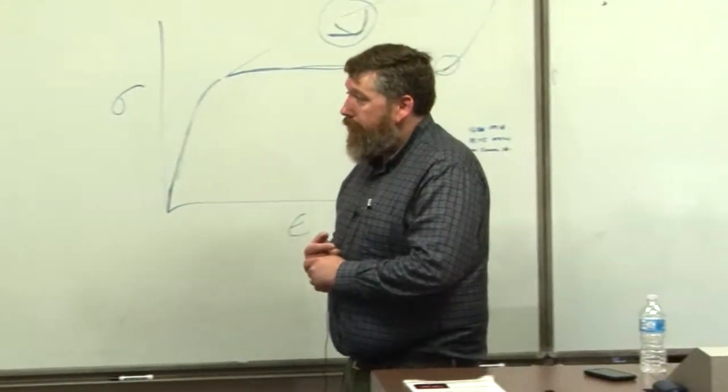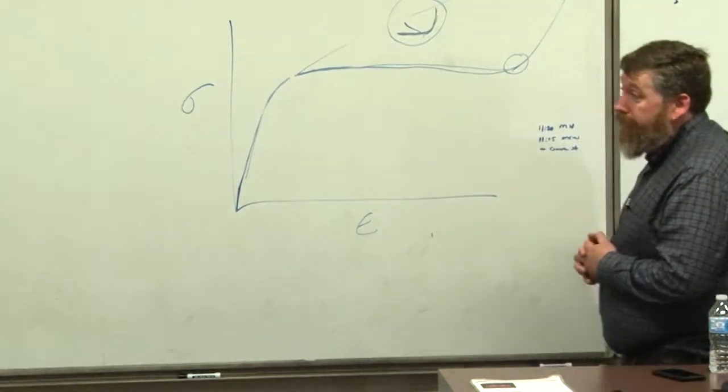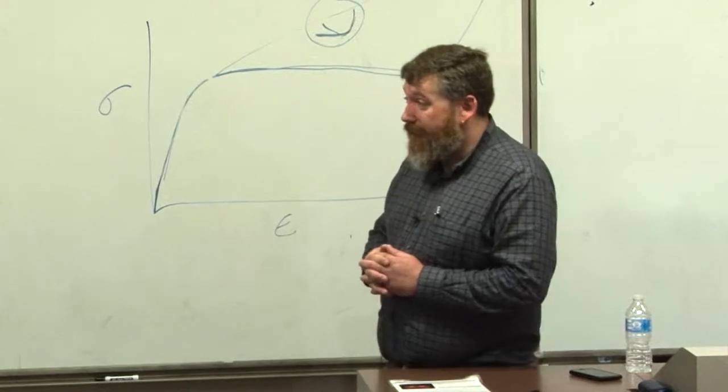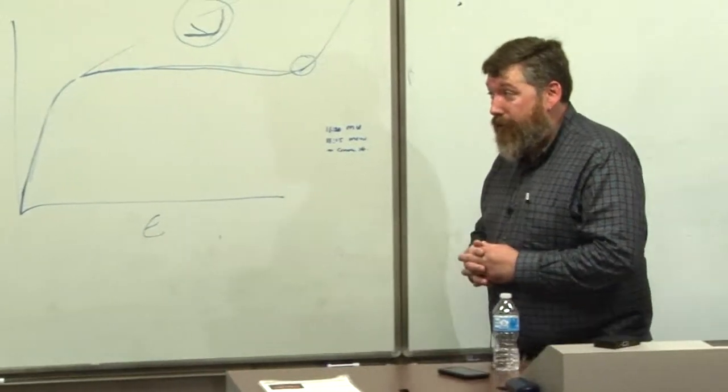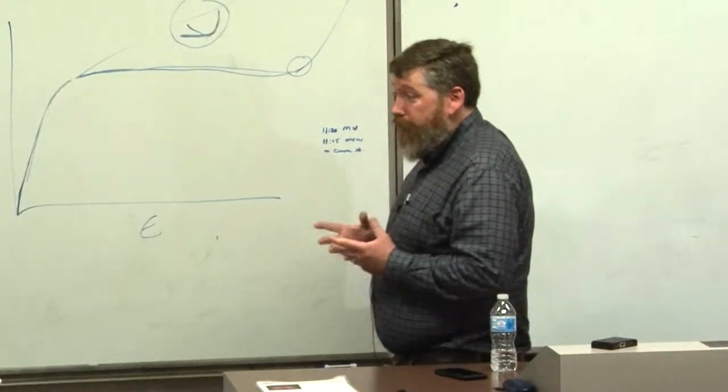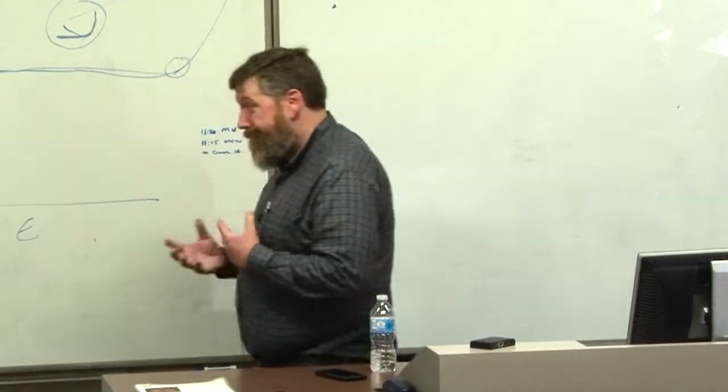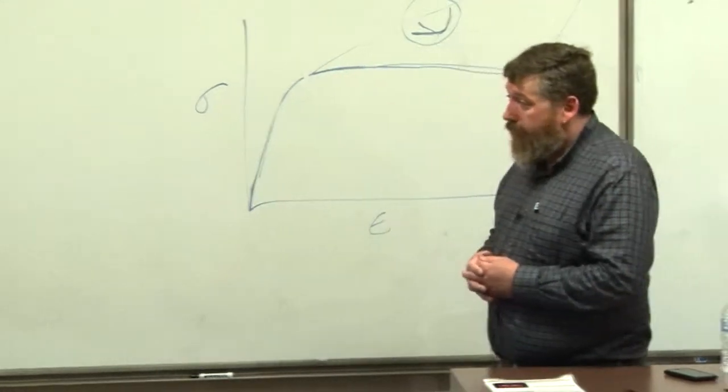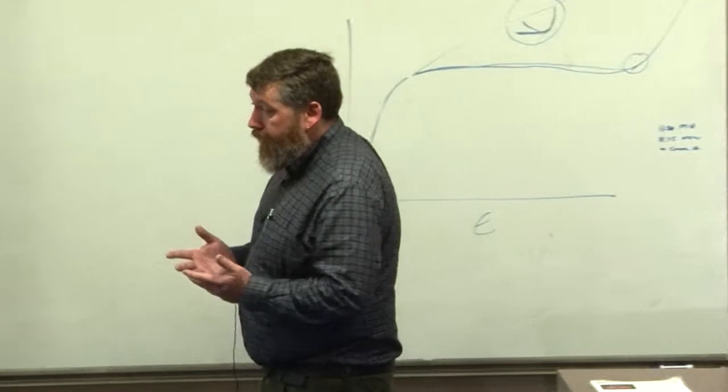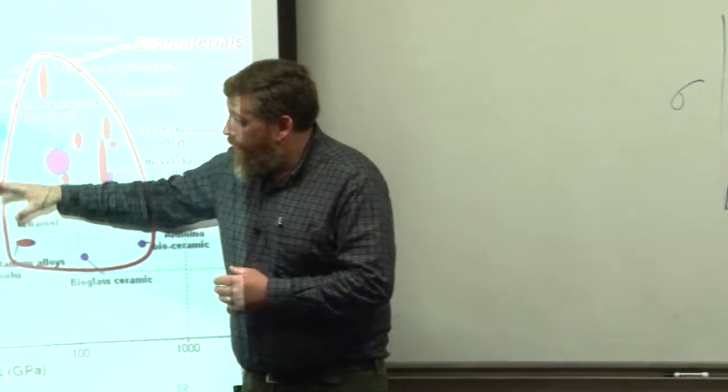So magnesium alloys that I've been working with have very attractive properties. They're very lightweight, but they are very difficult to cast. And there are at this time no 3D printing methods that are used to create magnesium components. So there's some difficulties in their processing that prevent that. But magnesium foams could be ideal bone implant materials because they can be custom made to match not only the structures but also the properties of cancellous bone.